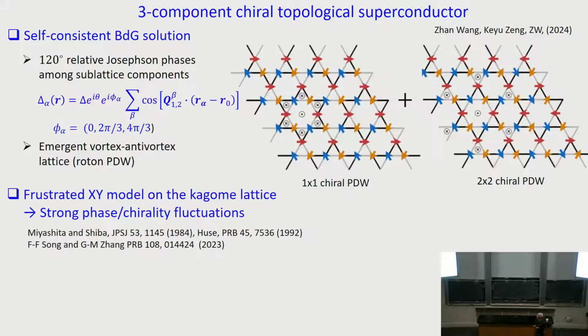Now, here is my last punch point. If I freeze the order parameter and only look at the phase of the superconducting order parameter, it looks like a classical XY model on the Kagome lattice, right? And that's something that has been studied, as I was introducing in the very beginning. Whether Kagome order, if I go beyond the mean field theory, Kagome order, that means this phase will be locked by 120 degrees. And we know it's not so easy because of these vortices, right? These chirality fluctuations. It doesn't want to order. In fact, it orders at even lower temperature than the crystal-melting transition. So it's appropriate to talk about it here. It has to be lower.